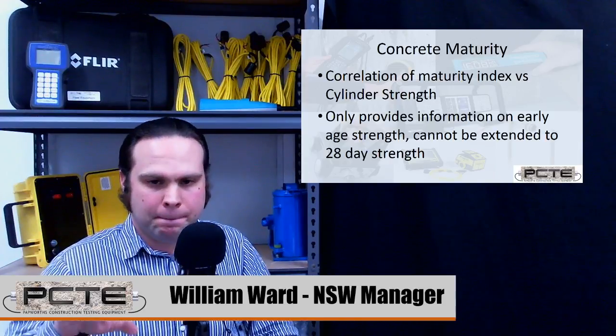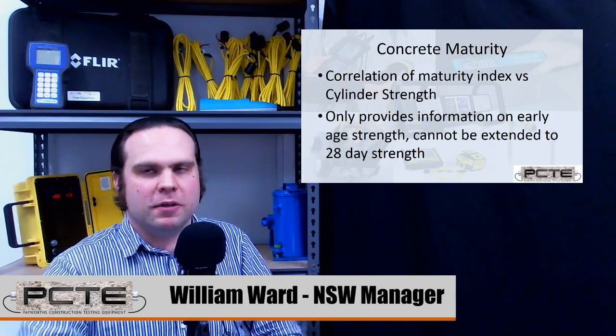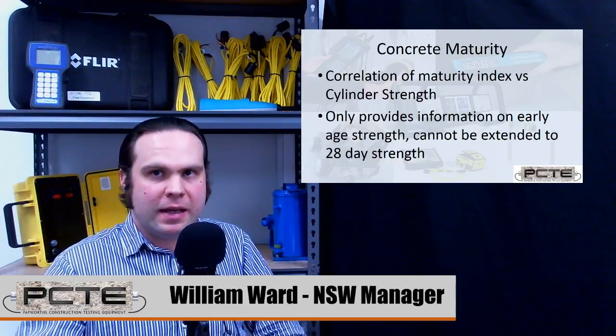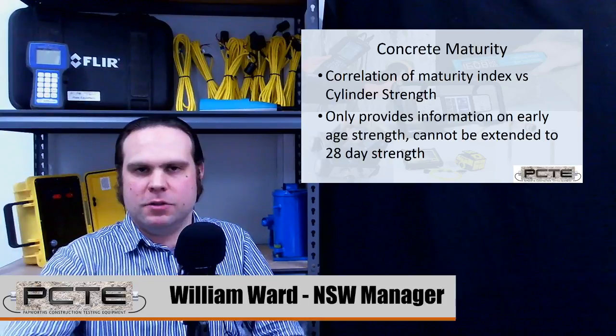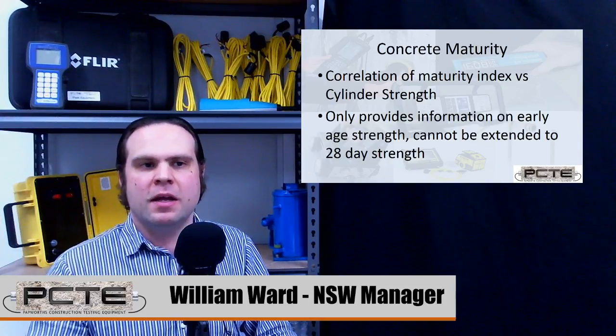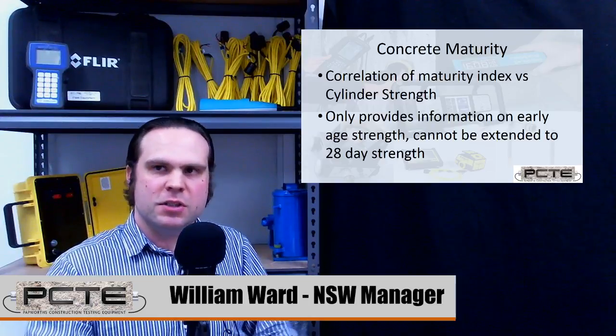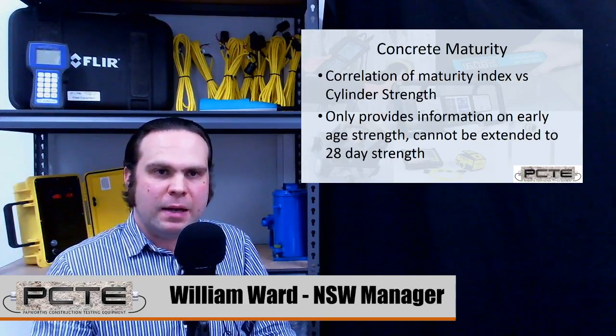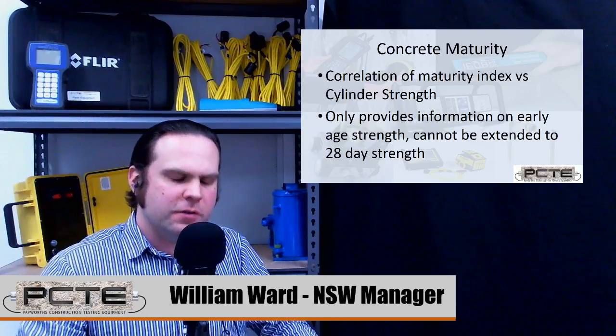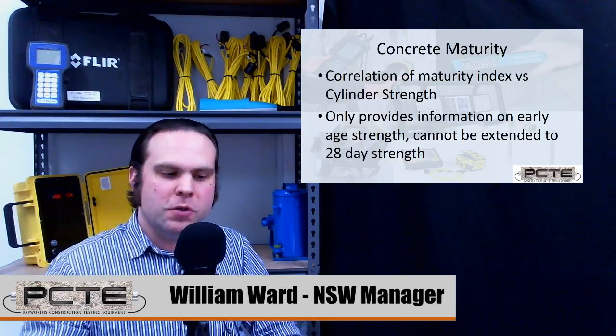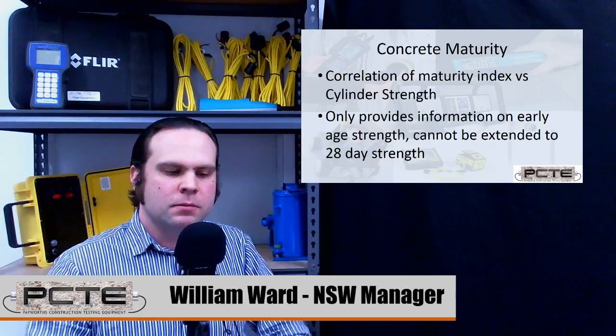The other relationship attempts to look at an equivalent age of concrete. So instead of looking in terms of a time degree centigrade unit, the unit is equivalent age. So if we've been curing this concrete in a standard curing condition, might be 23 degrees, might be 20 degrees, and it had been around for 50 hours at that curing environment, it would have an equivalent age of 50. Whereas if we go from a 20 degree age to a 40 degree age, and we cure for 50 hours, the equivalent age is now 100. More or less. The actual equations are in the final section, and there's more detail there, but that gives you the rough ideas of what these two indexes are used for.